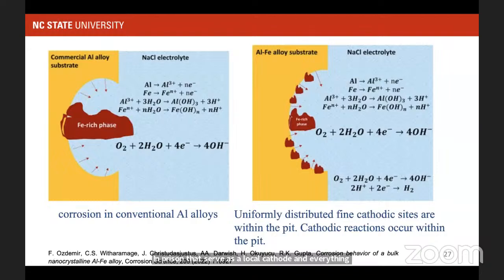that corrodes. Now you can think about if I have the same amount of inclusion, but you distribute that everywhere in the matrix, in a situation like over here on the right hand side, what could happen is that a pit could form. Once your pit has formed, inside the pit you have lots of cathodes sitting, and those cathodes, due to their cathodic activity, would produce lots of hydroxyl ions. Now, one necessary condition for pit growth is that the pH has to be really, really low. This could be like a 5 molar HCl situation inside the pit in that local environment. And these small cathodes would never let that situation come, and so the pit would not grow, right?